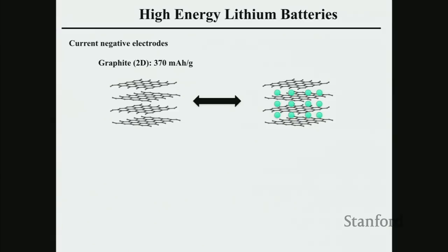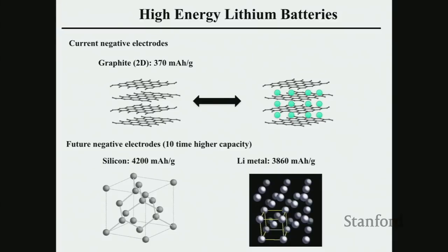In the past 27 years, graphite has been used as your negative electrode, that's the anode. And it has this layer structure, lithium intercalated into the graphite structure. This is the theoretical limit you can reach. We are about at that limit right now. There's very little room, very, very little room you can play with. But if you use new materials such as silicon or metallic lithium to store lithium ion, your capacity is 10 times more. It's 10 times more. So we have a chemistry right there for you to have a lot of room to grow.